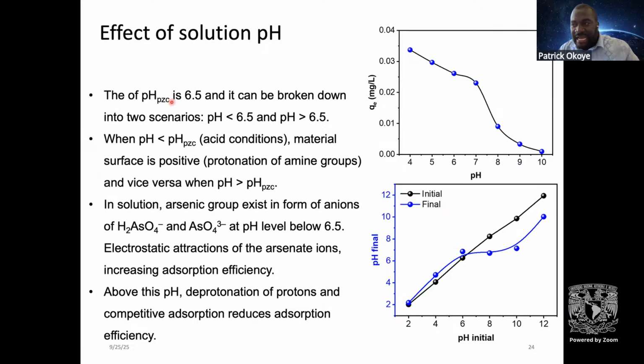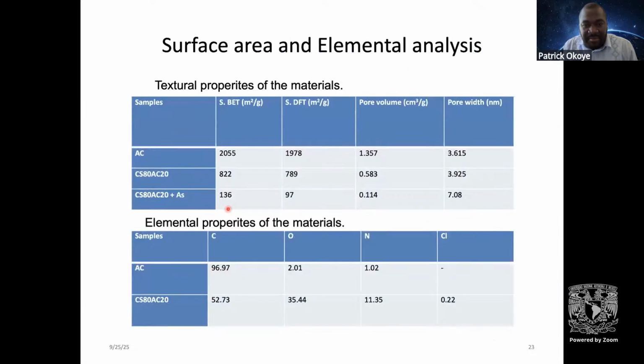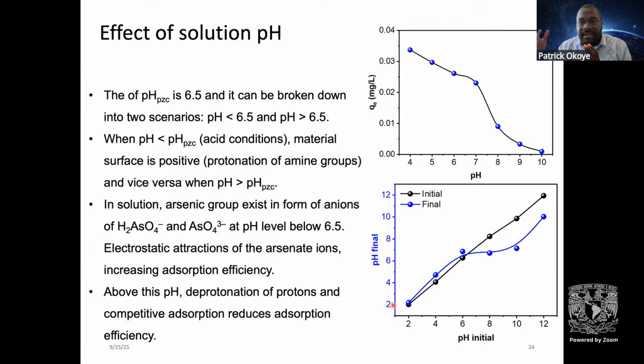The point of zero charge is the pH at which the surface of an adsorbent carries no net electrical charge, or is electrically neutral, and it is 6.5. We can break it down into two regions: from 6.5 down to 2, and from 6.5 upward. When the pH is far less than the point of zero charge, the material surface is positive, so we have some protonated amine groups in the chitosan. Remember, we have a lot of nitrogen, so this nitrogen infers an amine group. And the reverse happens when we go from 6.5 to 12.